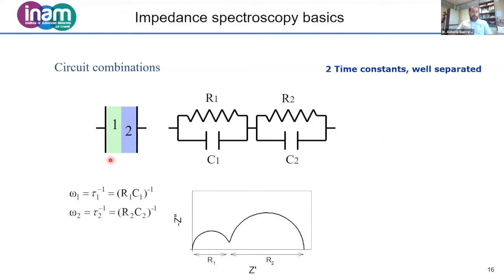If we have more than one process, and we have, let's say, two layers, and both of them are semiconductors, or they are not purely conductors, or not purely capacitors, and the time constants of both of them are very well separated and resolved. So let's say they have different orders of magnitude in seconds for the characteristic time. In that case, we will see two arcs which are well resolved. This is usually not the case.